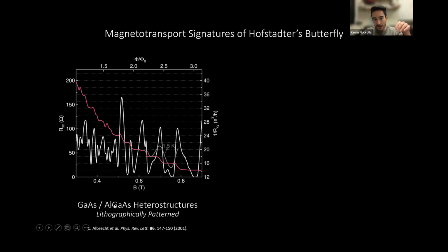In addition, the authors used lithographic techniques to drill holes in the aluminum gallium arsenide, and they evaporated a top metallic gate onto the surface, such that as a function of real space, the distance between the gate and the 2DEG changed laterally. But in addition, the places in the heterostructure where the Fermi level is pinned was changing as well. So both of these effects cause this large wavelength superlattice potential that is written by man. This is written by the parameters that you use in lithography.